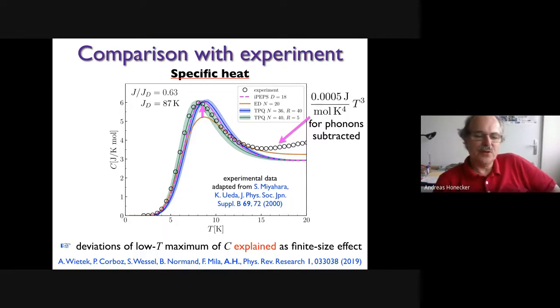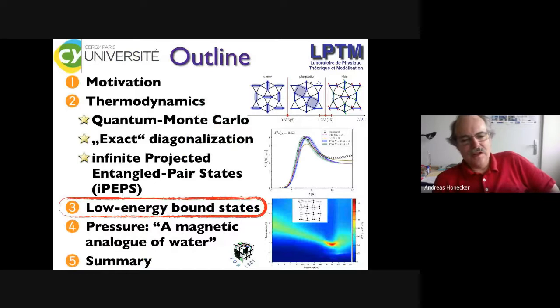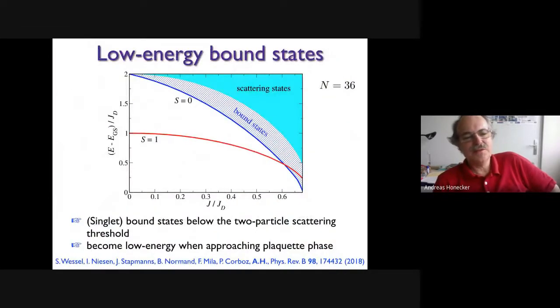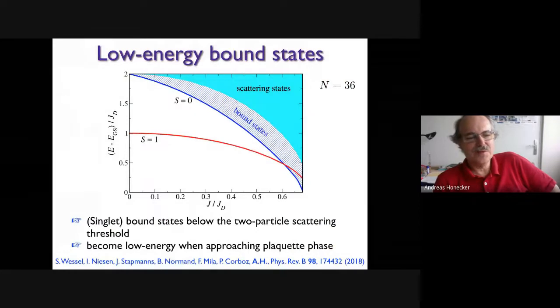I should maybe insist here that if you look at this, so people might have known this, the characteristic energy scale in C here is 10 Kelvin. So the maximum is on the order of 10 Kelvin, which is not the scale that you got from neutrons, which is 35 Kelvin. It's a much lower energy scale. Now, the question is, where does this low energy scale come from? Let me very quickly comment on that.